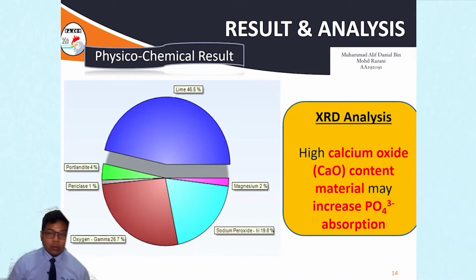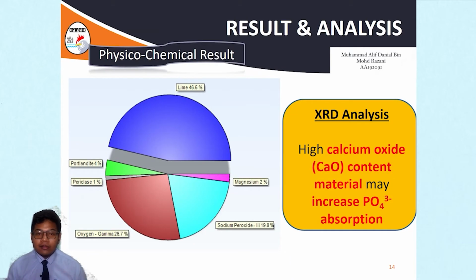Finally, the last method that we used to analyze the result in this study is X-ray diffraction analysis, or XRD. XRD is a technique used in material science to determine the crystallographic structure and identification of a material. If you look at the result in this study, it shows that calcium oxide is higher compared to other chemical content. This high calcium oxide content may increase the phosphate adsorption and may help this study succeed.